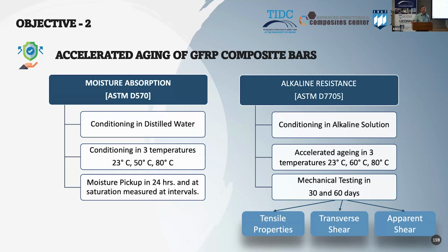We also look at alkaline resistance. This is a requirement from the guidelines because in fresh concrete, the bars will be exposed to an alkaline environment. Of course, when the concrete cures, that will not be the case, but there is a time of exposure and the codes call for this. We do this also at different temperatures. Next.